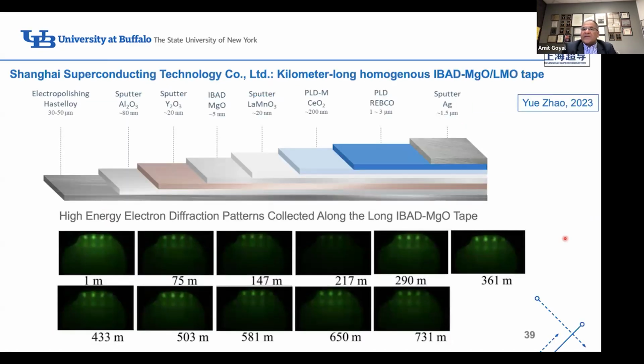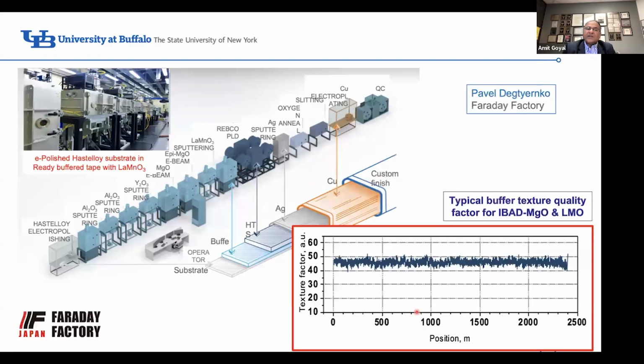Here's another example from another company out in China called Shanghai Superconductor. You're looking at reflection high-energy electron diffraction patterns taken at 1 meter in the length and 731 meters. Very nice and constant substrates can be made, and superconducting wires. Here's another case, from Faraday Factory in Japan. Again, they've got the same configuration that I mentioned previously, LMO by sputtering in this case, then they deposit superconductors by PLD. Again, you're looking at the texture of the lanthanum manganate layer over a close to 2.5 kilometer long wire, very constant.